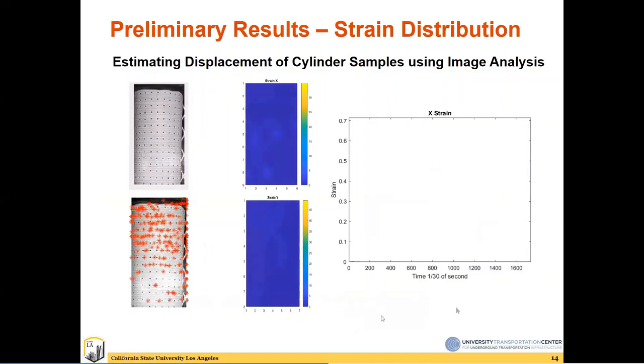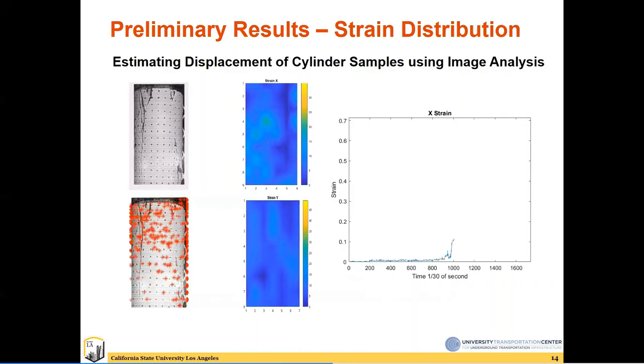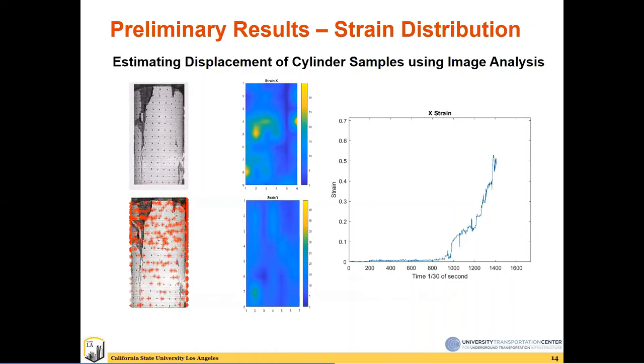One other thing that we've been working on is that we're trying to extract the strain or deflection properties of the cylindrical samples under compressive strengths using image analysis techniques and see if we can correlate the compressive load and the deformation and find the load versus deformation or stress deformation curves by just recording the test and then using some image analysis techniques to evaluate the X and Y displacements of the sample.